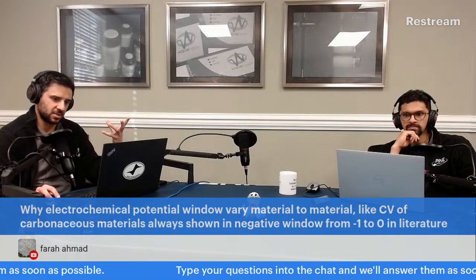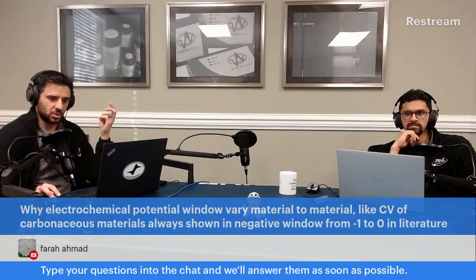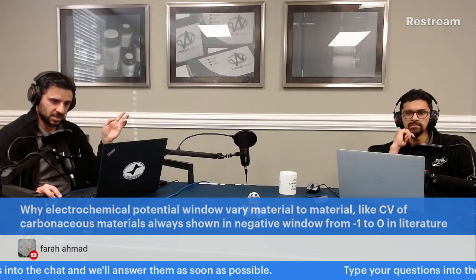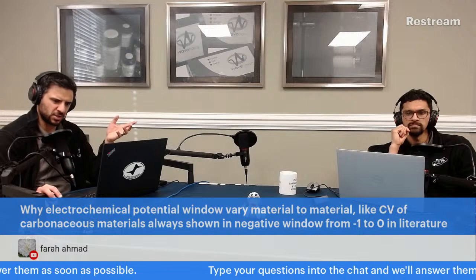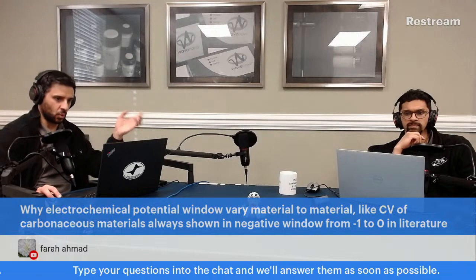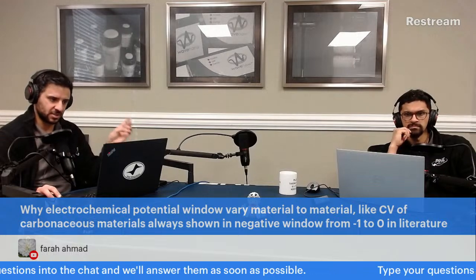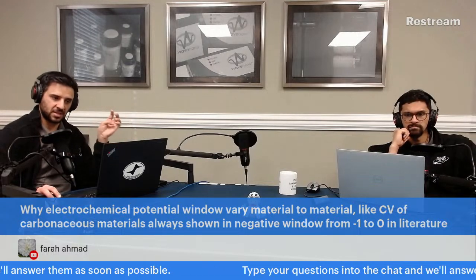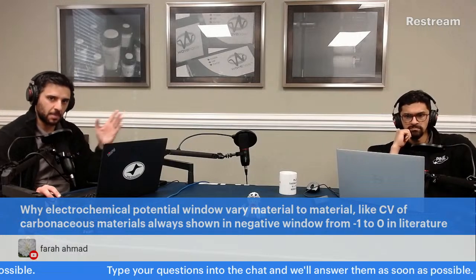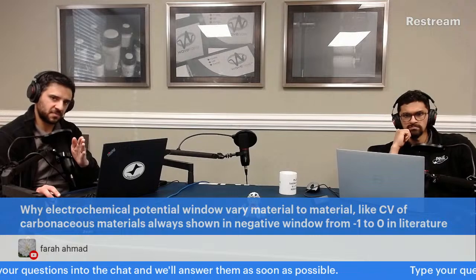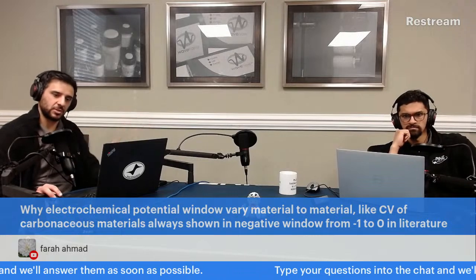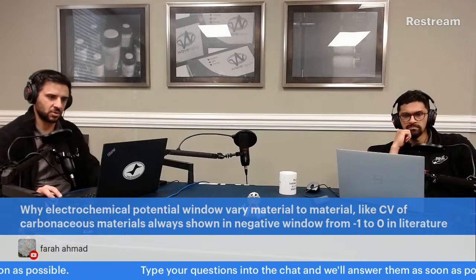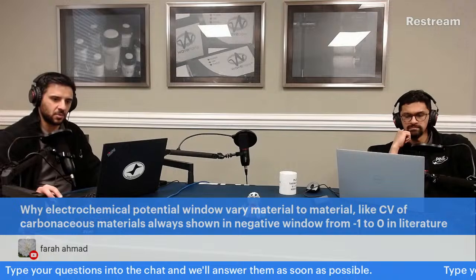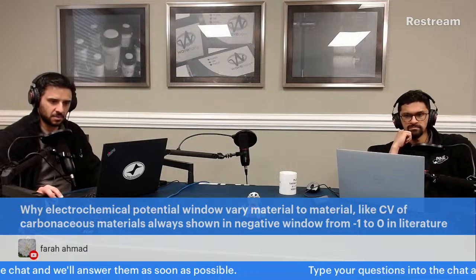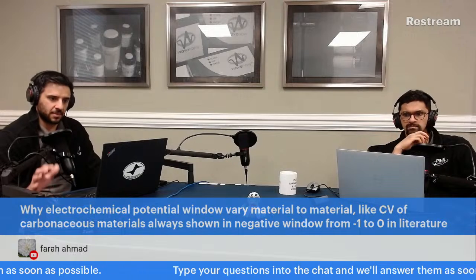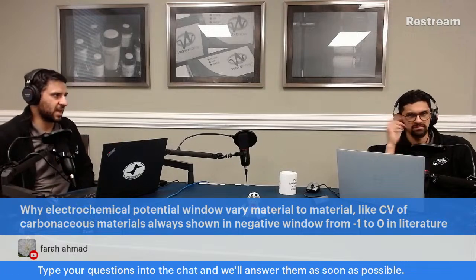I wanted to piggyback off what Alex just did. The point is that one of the reasons you might see a shift of potential windows is not necessarily because of the material, but because of the pH. If you're working in pH 1 or pH 14, you'll have almost 800 millivolts difference in the potential window. As the pH goes up 14 units, all the features shift negatively by 60 millivolts per pH unit. It's related to the Nernst equation because it's proportionate to the amount of H plus, that equilibrium, that shifts it. And then the other possibility is, in general, different catalyst materials behave and perform differently.